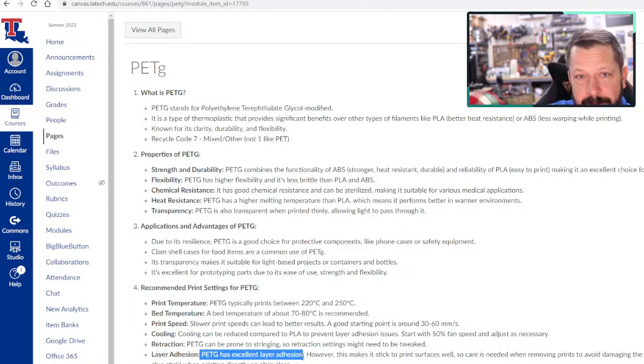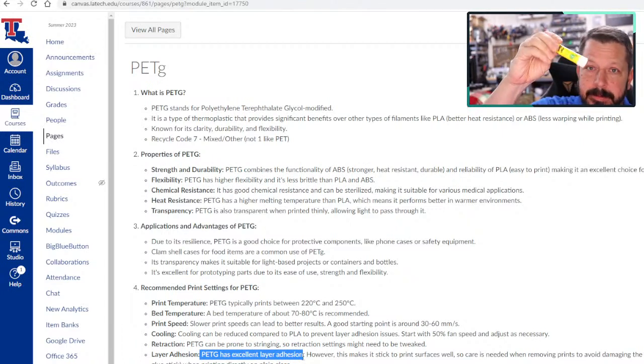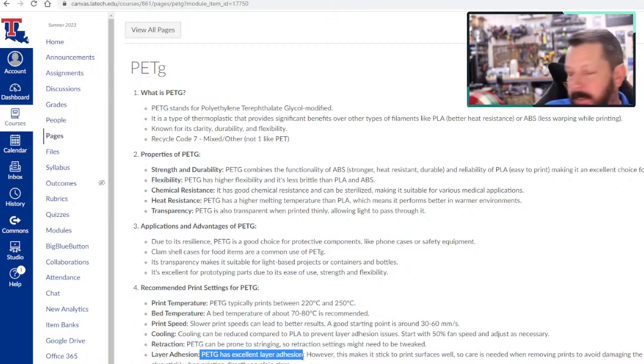Because if you print it straight onto plain glass, now this bed on here is not plain glass, it has a texture on it, like a little PEI dots on it or something. But if you print it straight on plain glass, there's a good chance that it will bond strong enough to that glass that in order to get the part off, the glass ends up breaking, or even chunks of the glass pull out. So if you do print PETG on glass, I would definitely put down some glue stick, or if you don't like the surface that glue stick does, then just do some hairspray.